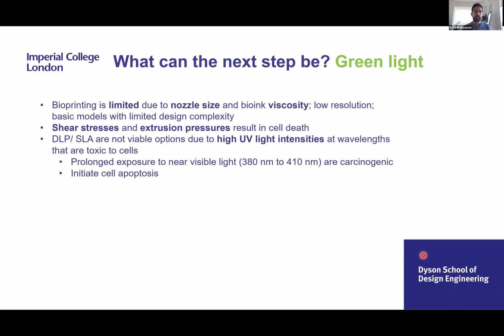If you were to use a DLP and SLA, they will not be viable as they have high UV intensities at wavelengths that are toxic to cells. So prolonged exposure in the near visible light spectrum, 380 to 410 nm and slightly higher, is carcinogenic and initiates cell apoptosis. So all visible wavelengths of light can be toxic to cells in vitro, depending on the dose and the wavelength, with the more energetic, shorter wavelengths of light below 500 nm particularly being detrimental.